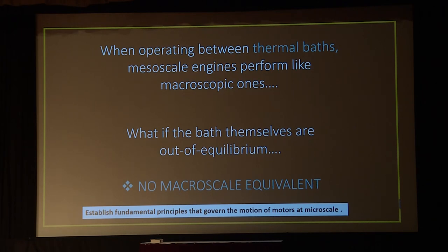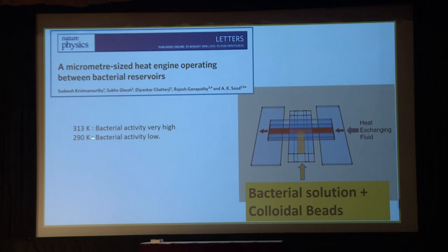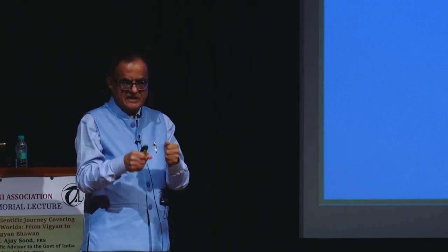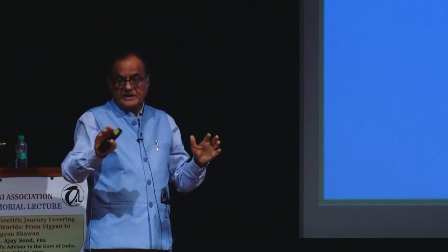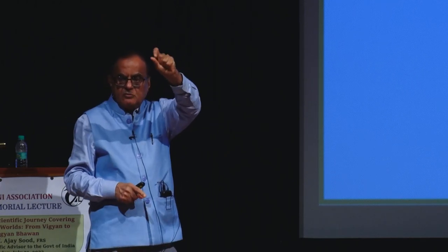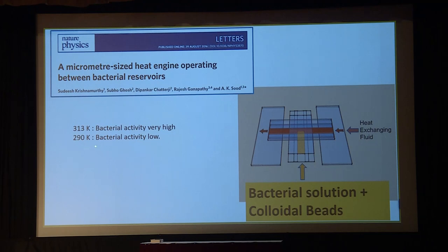How do we do that? This is what we did in 2016. In this work, in addition to the colloidal particle, we also put bacteria into it. And the temperature of that whole bath, by another channel, we varied between 313 Kelvin, a little bit feverish, and 290 Kelvin. At 313, bacteria are very, very agitated. They really move around. Bacteria are not trapped. Trapping is still one single colloidal particle. But at 290, they do not die, but they are very sluggish.